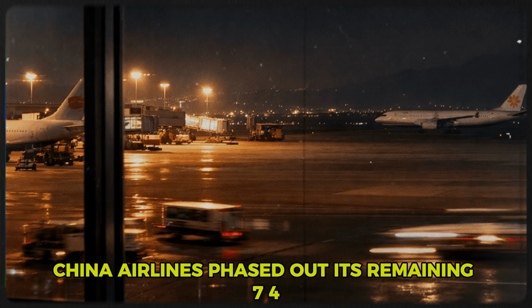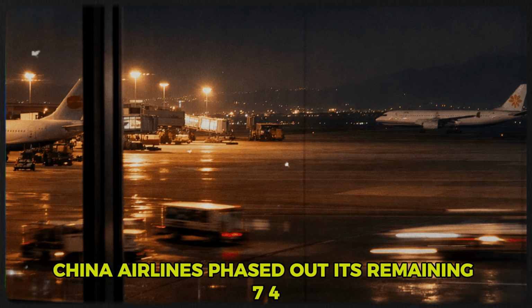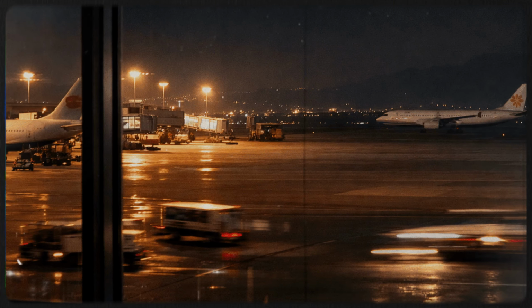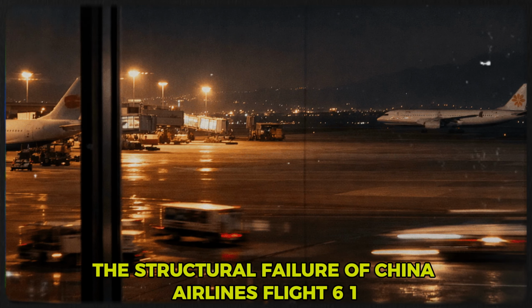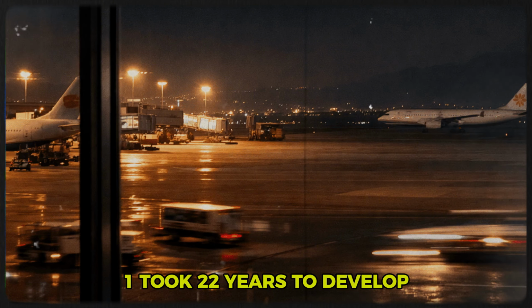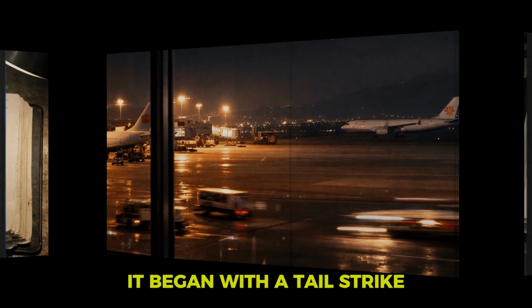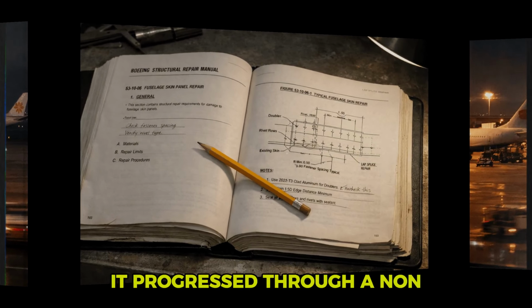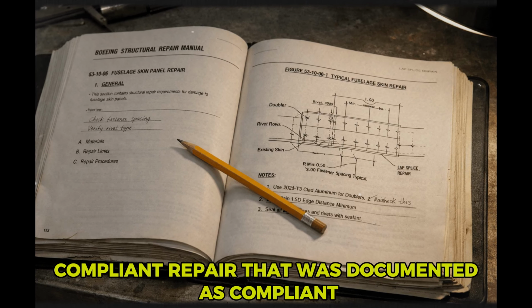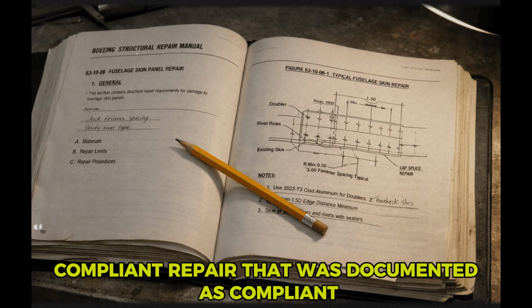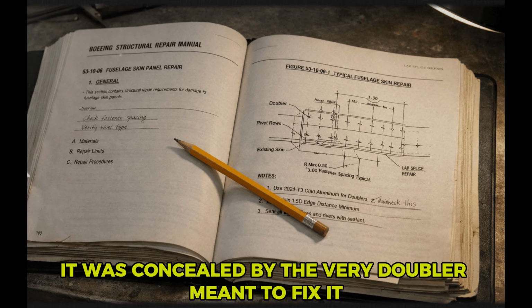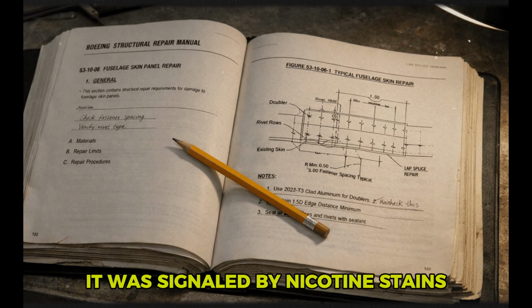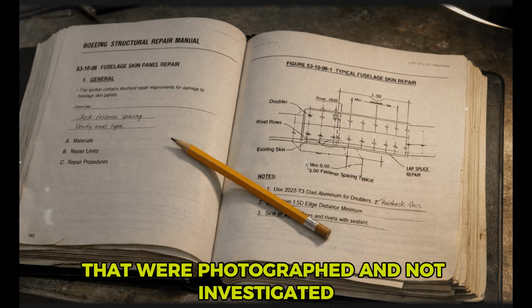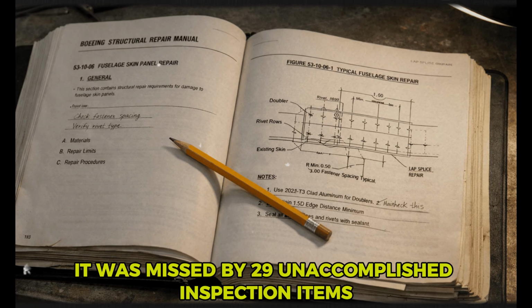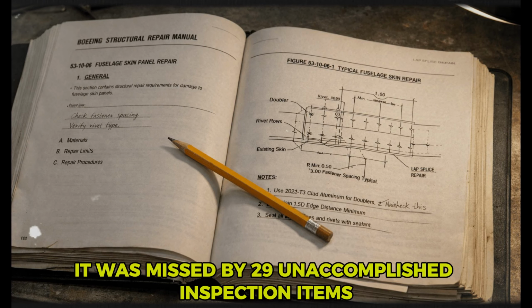China Airlines phased out its remaining 747-200 fleet. The structural failure of China Airlines Flight 611 took 22 years to develop. It began with a tail strike. It progressed through a non-compliant repair that was documented as compliant. It was concealed by the very doubler meant to fix it. It was signaled by nicotine stains that were photographed and not investigated. It was missed by 29 unaccomplished inspection items.